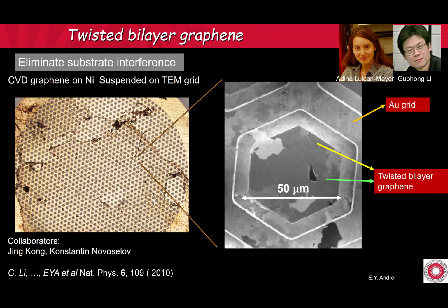This is the grid. The holes are about 15 microns. When you do chemical vapor deposition, you can have very large samples. And this was grown by Jing Kong at MIT, using not the standard growth on copper, she grew it on nickel. And what we didn't know at the time is that when you grow graphene on nickel, you actually grow bilayer, and they're twisted. The twist is kind of random. So when we looked at one of the suspended samples, you get twisted bilayer, and every possible twist angle is there.